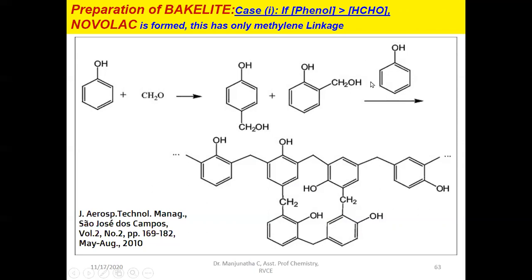Again, because of the presence of more phenol in the reaction mixture, the unreacted phenol reacts further with the formed intermediates. Monomethylol phenol and ortho and para methylol phenol combine with phenol, resulting in the formation of a mostly linear structure. The polymer formed is called novolac. Each monomethylol phenol group is linked via methylene (CH2) linkage. The CH2–OH reacts with the H of phenol: H from one group and OH from another combine to form water, and CH2 links to the para position of the phenol.